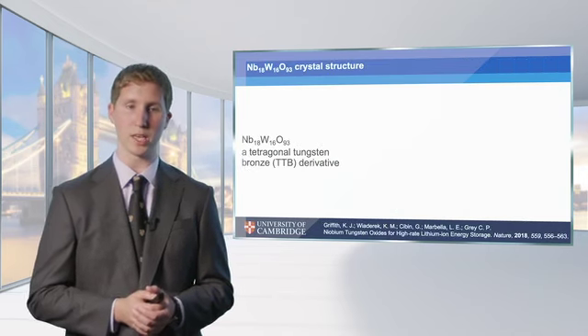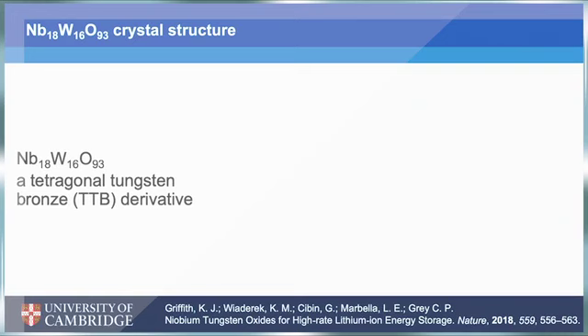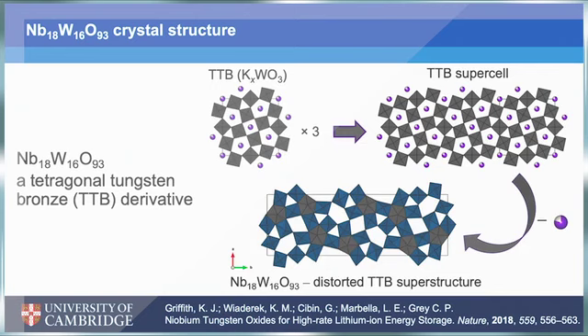And so if we think about how we get there, the Nb18W16O93 crystal structure is really a bronze derivative of the tetragonal tungsten bronze. And so we can envision how that analogy plays out here. So in the tetragonal tungsten bronze, we have partially reduced tungsten, which forms a corner sharing octahedral network that's stabilized by some intercalant, say potassium in this example. And if we imagine a supercell of that tetragonal tungsten bronze, we can see the parallels between that distorted corner shared network and the blue distorted corner shared network in the NWO bronze.